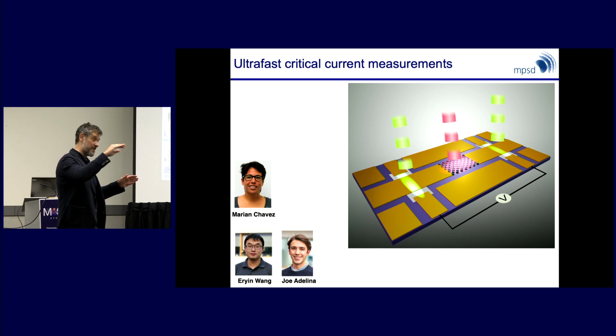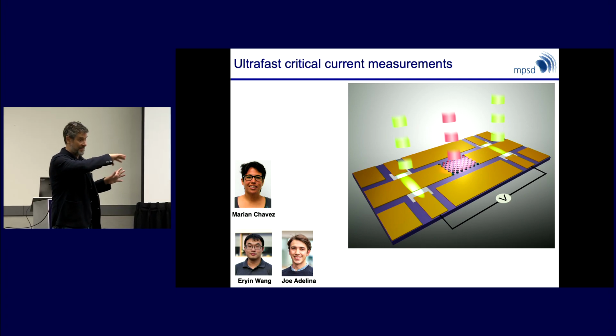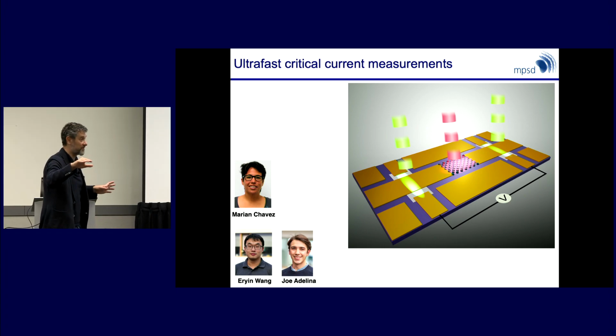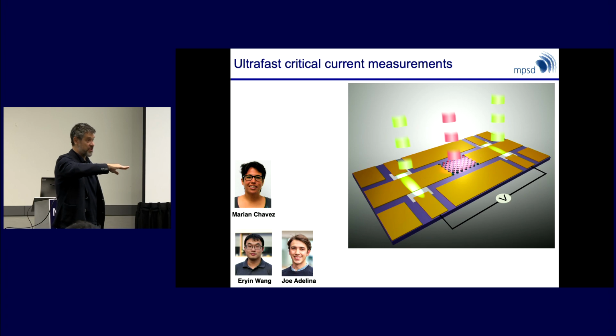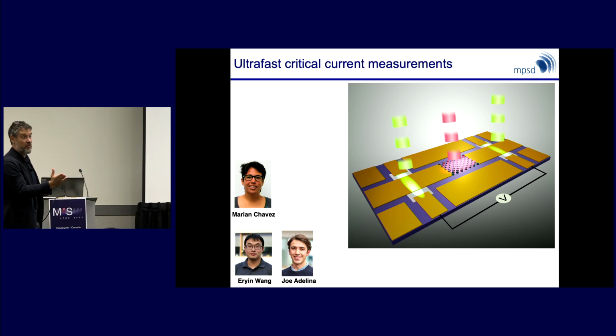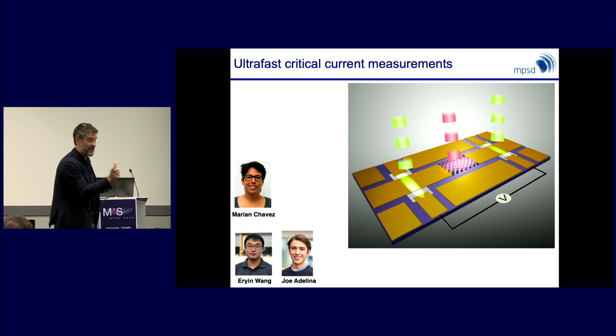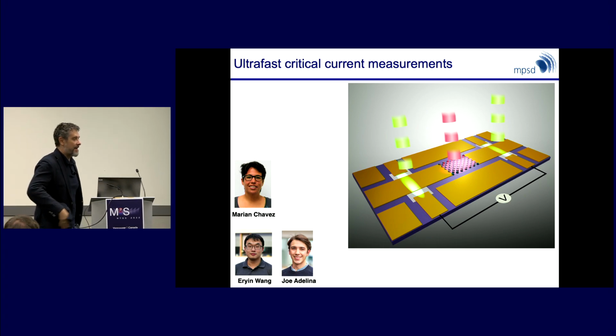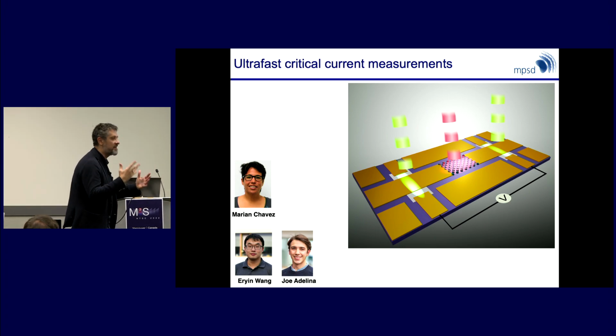But then we rely on the fact that the state is long. I've shown you only one snapshot now. Of course, once we learn how to do this, we'd like to characterize this effect as a function of time. And for example, it's very interesting to see maybe this relaxation time. At some point, this thing is going to become a metal, maybe after only 10 picoseconds, and then the nonlinear current response will go away, right? So it's, of course, a very good experimental question to ask. How long will the nonlinearity last? Again, this is just hard enough that we haven't gotten to it yet.